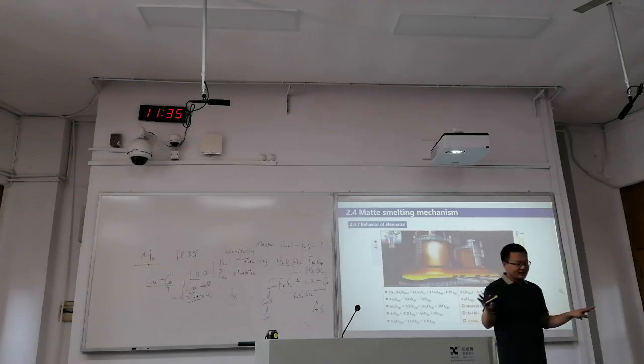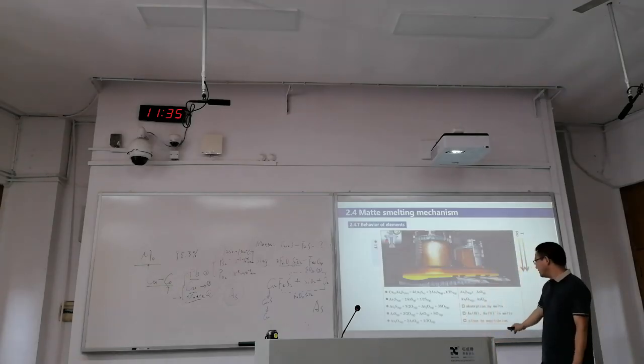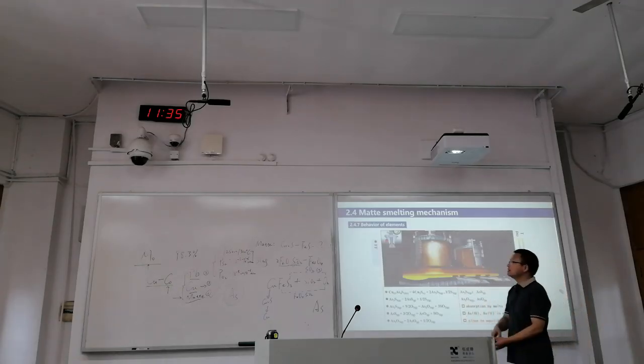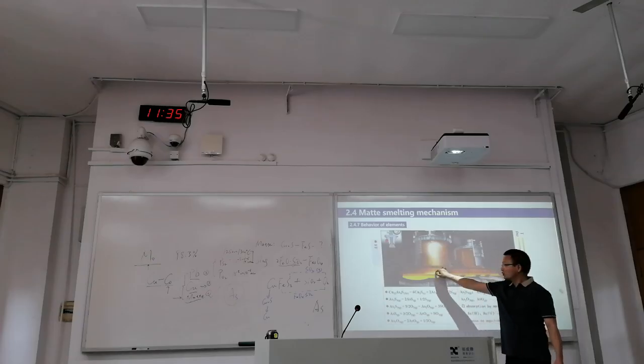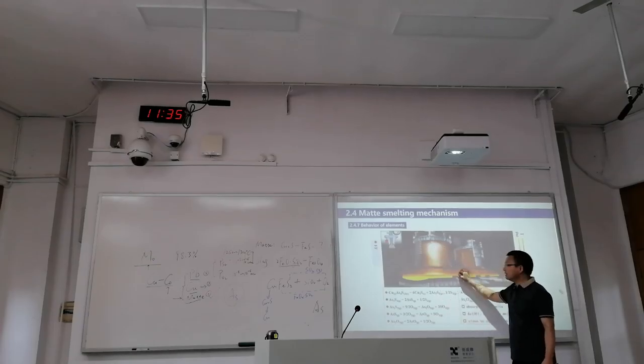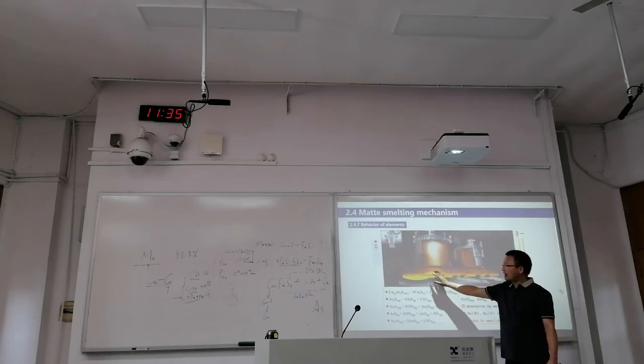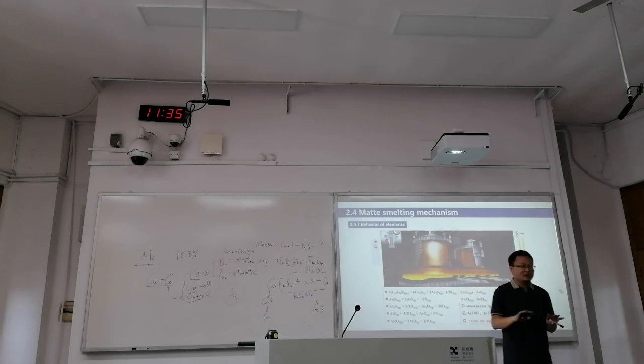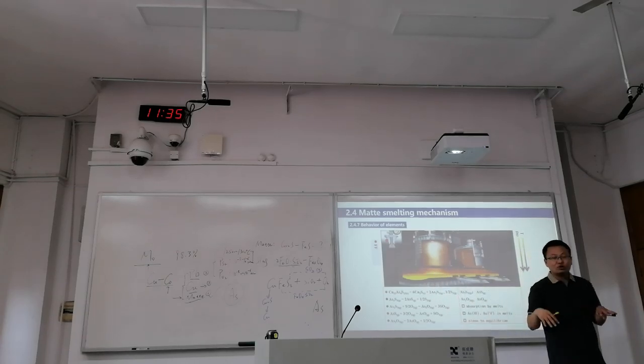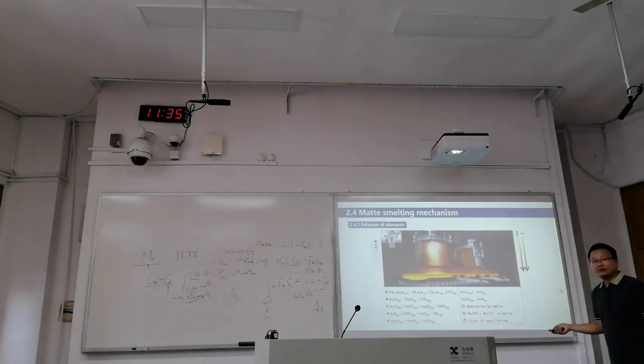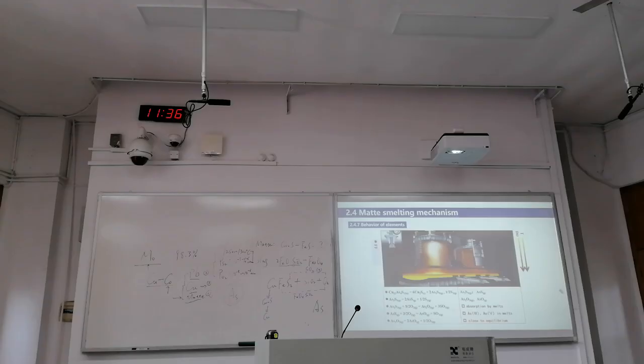So they have tendencies. This is very close to equilibrium, and they are moving along during the settling. So this is why after entering this settler, the solubility, the dissolving of arsenic in the matte and in the slag, is close to equilibrium. So this is in this furnace.